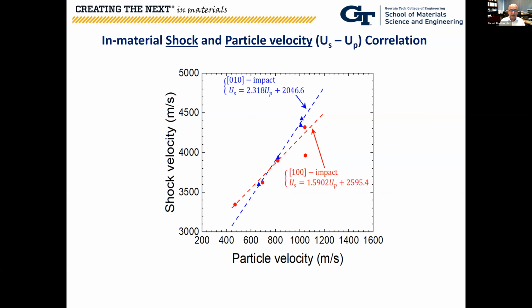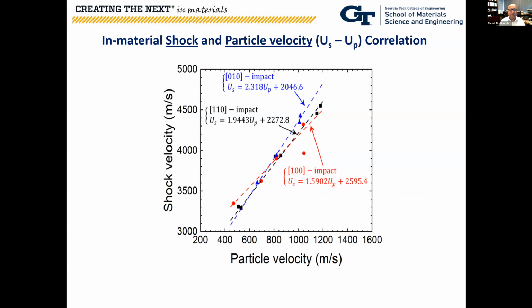If we consider the 010 orientation, again we have 4 data points, and you can see there's a slight deviation from the 100 orientation. Then when we come to the 110 orientation, again we have 4 or 5 data points.